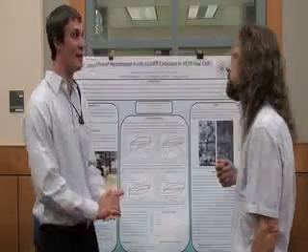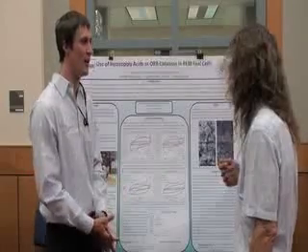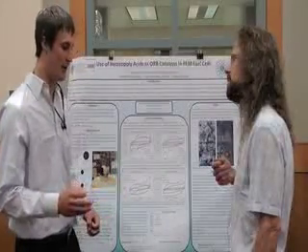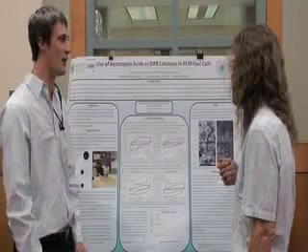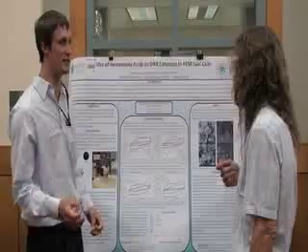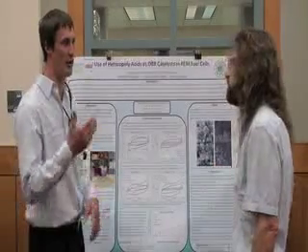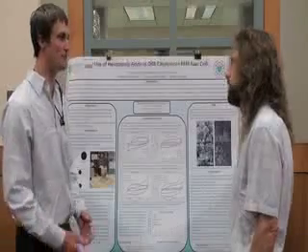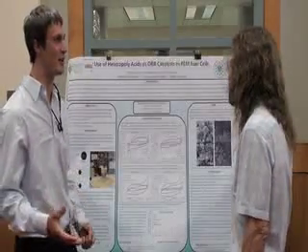And so the platinum and platinum alloys are really expensive, and you have to use high loadings of them. And also, they're not fully efficient, so things like carbon monoxide kill the catalyst. And so the hope is heteropoly acids are already being used in some proton exchange membranes for the membrane itself. And we're hoping that we can use the heteropoly acids as a catalyst.